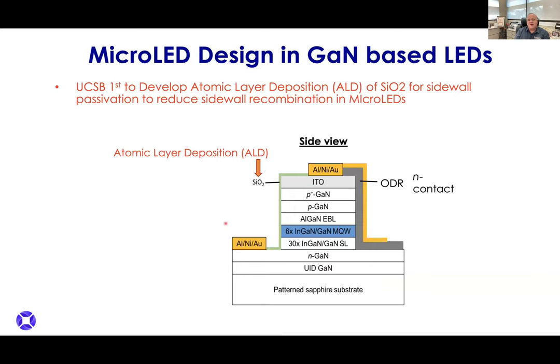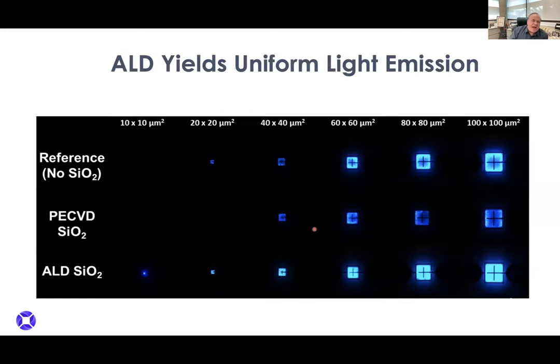But we were the first research institute to solve that. And we employed a new technology of atomic layer deposition, which was primarily being used in the silicon industry, and it was not being used in the LED industry. And basically in 2018, 7 years ago, we employed that to passivate the sidewall here of the micro LED, because as you reduce the size of the LED, the sidewall becomes very important to what's going on in the active region.